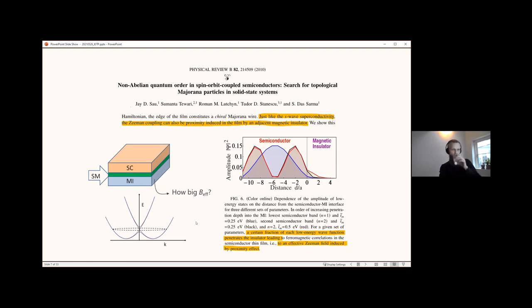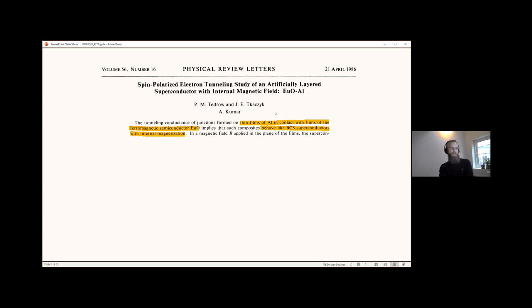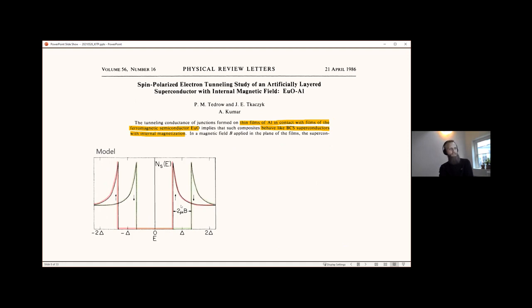Searching through the literature a little bit, going as early as the 80s, I found an experiment on europium oxide aluminum bilayers, where the finding was that thin films of aluminum in contact with films of the ferromagnetic semiconductor europium oxide behave like BCS superconductors with an internal magnetization. Their model is that the exchange coupling between the europium oxide and aluminum spin splits the density of states in the superconductor, which can be approximated by the Zeeman energy. And from the peak splitting, you can extract the effective magnetic field.